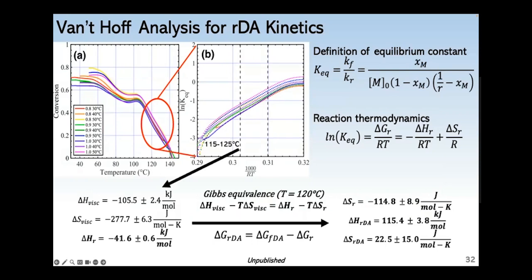So after I've converted all the temperature ramp data of complex viscosity to conversion, I get the left plot A. And to me, it seemed like the conversion curves might roughly overlap each other. So I decided I'm going to make the argument that this is kind of like a quasi equilibrium, even though I'm ramping up in temperature. And what that allowed me to do is then plot the log rate, or log equilibrium constant, calculated from the conversion onto an inverse temperature plot. And from fitting a line there, you back out the enthalpy and entropy of reaction.